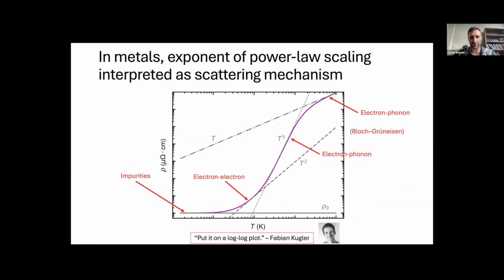In metals, we go a step further and we interpret the different power law regimes as indicating different dominant scattering mechanisms. At low temperature, we have this temperature-independent residual resistivity coming from disorder and impurities. Then we have an electron-electron part at low temperature that will be T squared if we have a Fermi liquid. And then at higher temperatures, usually we assume that electron-phonon scattering takes over, and in the so-called Bloch-Gruneisen picture, we have a T to the fifth scaling of the resistivity that turns into a T-linear scaling. We can see this all nicely if we put the resistivity on a log-log plot.